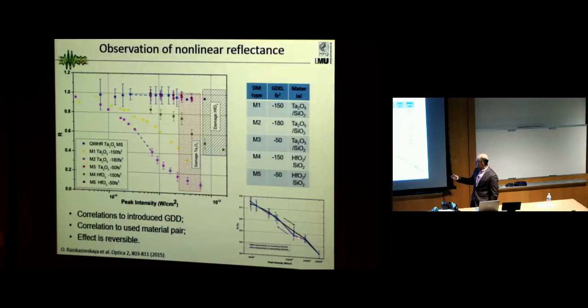No, in this particular case, we don't have any hysteresis curves. It's really just returning the same way. And actually, we tried different mirrors with different dispersion, with different material, and we found out that the mirrors with higher GDD have a much stronger effect than the mirrors with smaller GDD.